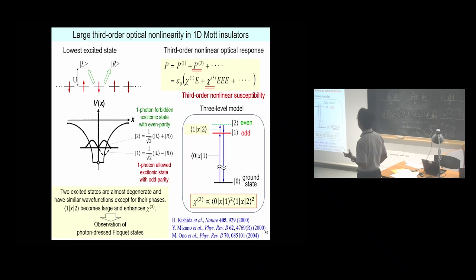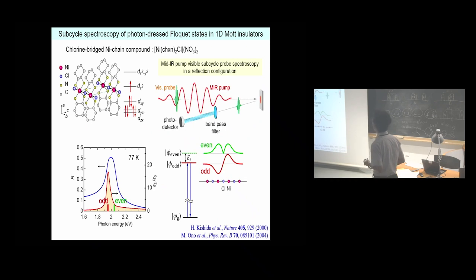Such a large optical nonlinearity makes us expect to observe clearly the photon-dressed Floquet state. The studied material is another typical 1D Mott insulator, that is, a chlorine-bridged nickel-chain compound. In the absorption spectrum, the sharp peak due to the odd parity exciton is observed at 1.95 eV, and the even parity state is located just above the odd parity state.